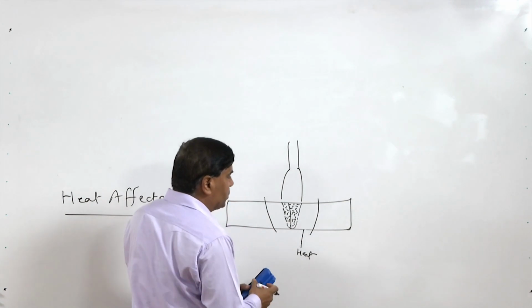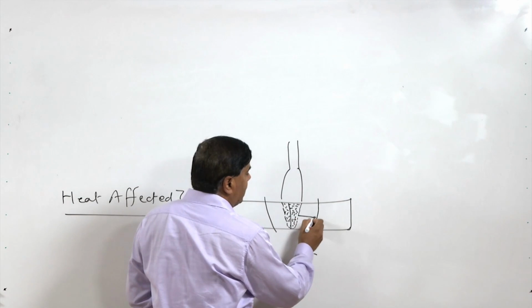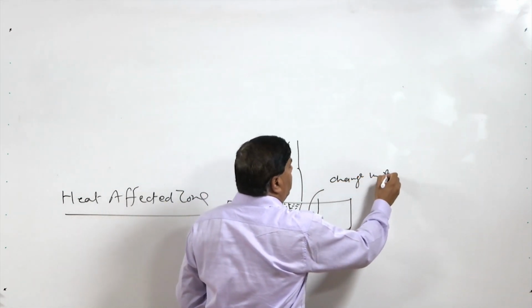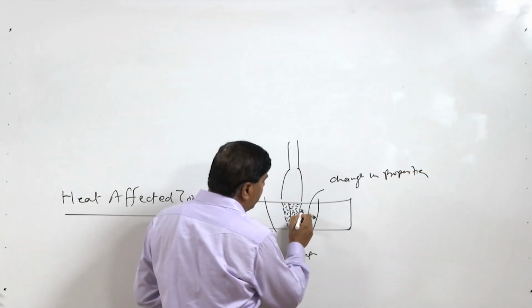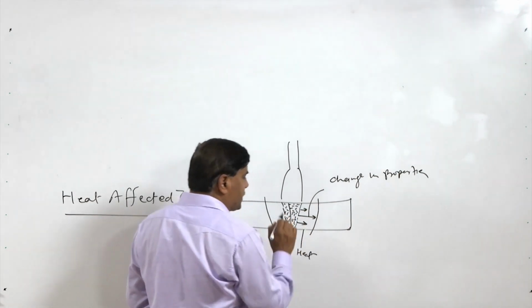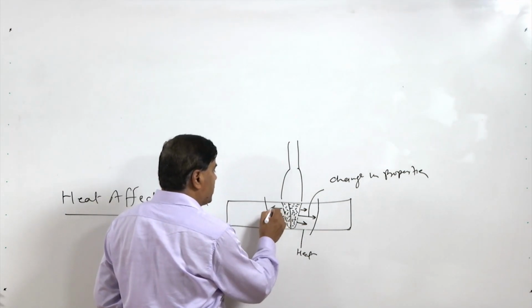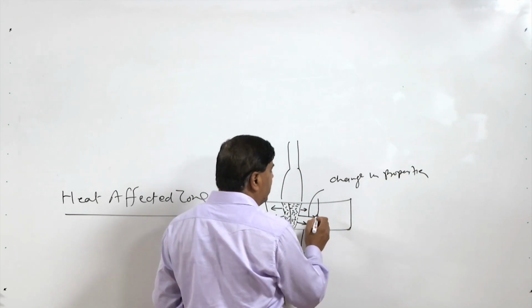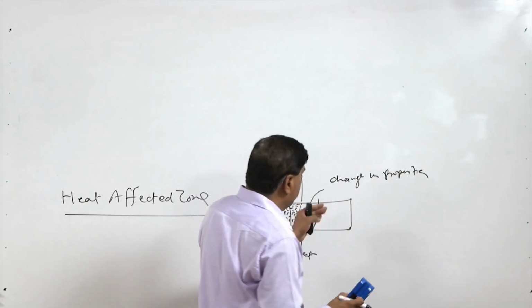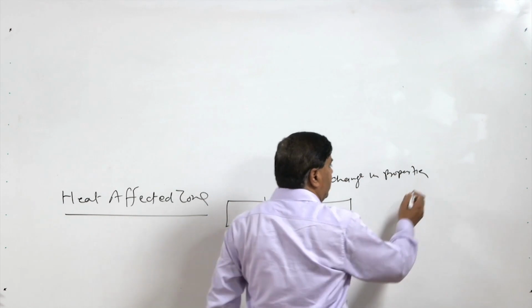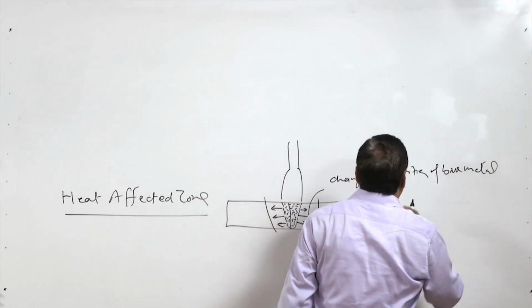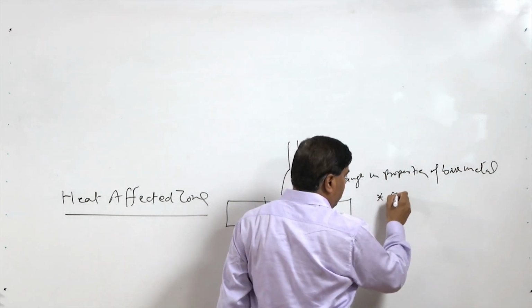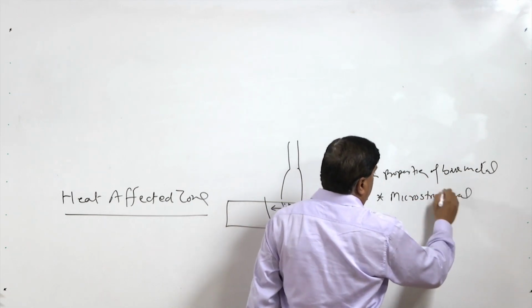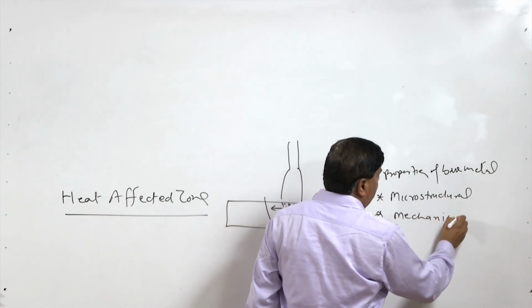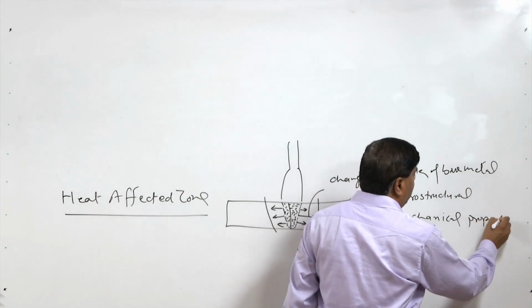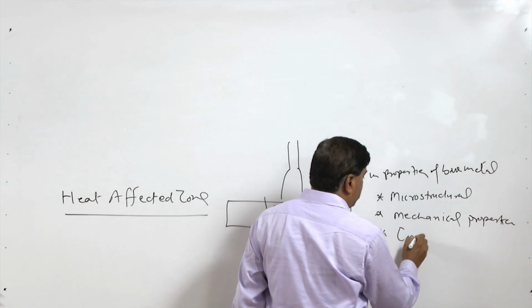But up to what extent the heat affected zone will be formed depends upon the distance up to which the change in properties is observed. Heat will be transferred from the fusion zone to the base metal side, in both directions, and due to this heat there will be a rise in temperature. The rise in temperature up to a particular limit for a given metal will cause a change in properties of the base metal. This change in properties may be in respect of microstructural variation or mechanical properties, wherein either hardening or softening of the metal in the heat affected zone can take place, or there can be loss of corrosion resistance.